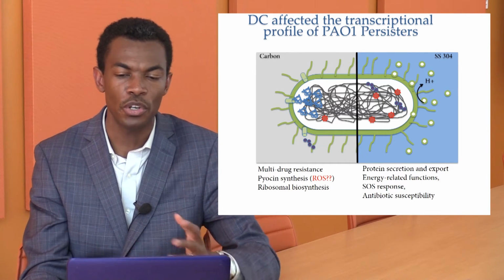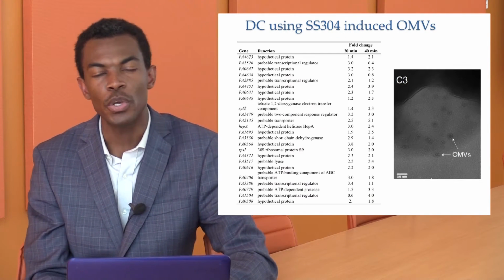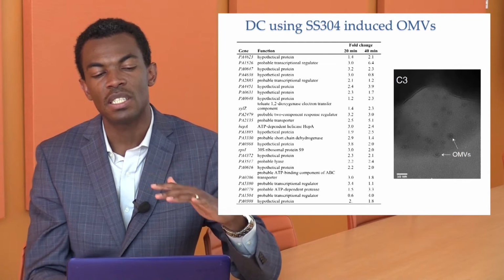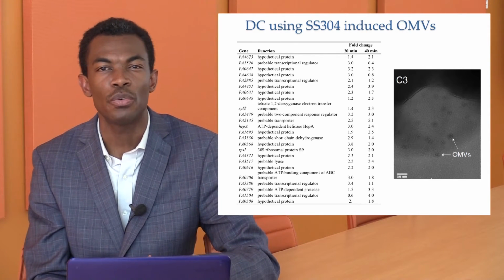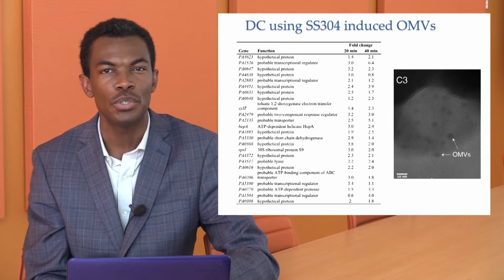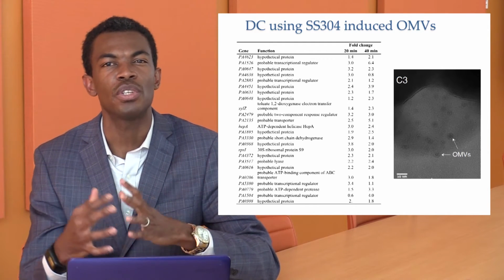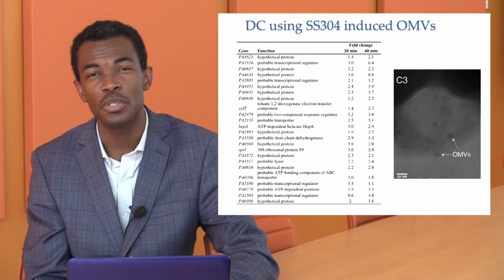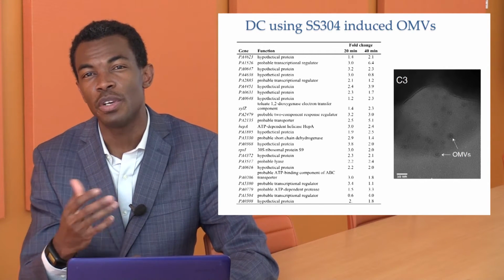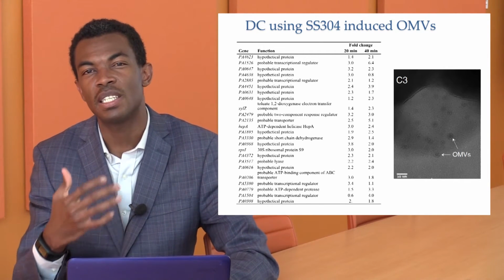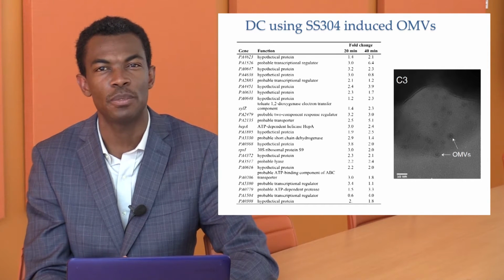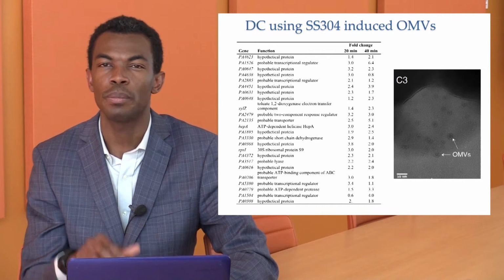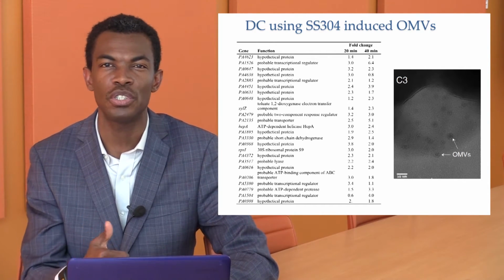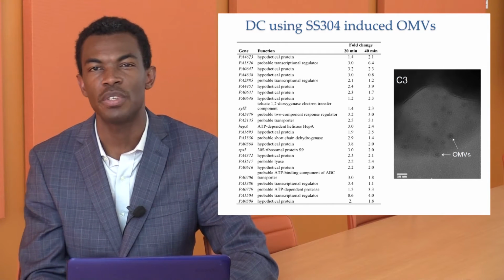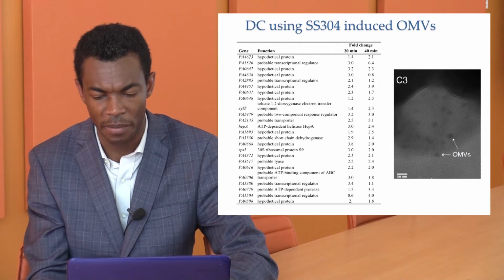And if we go further, still using the genetics, we could see a bunch of genes related to the secretion of OMVs that were all induced under the conditions of 20 minutes and 40 minutes. That means the secretion of OMVs starts even earlier, when the cells start experiencing the accumulation of this waste product inside themselves. Automatically they tend to respond by inducing all these genes and secreting the OMVs, as we saw previously.